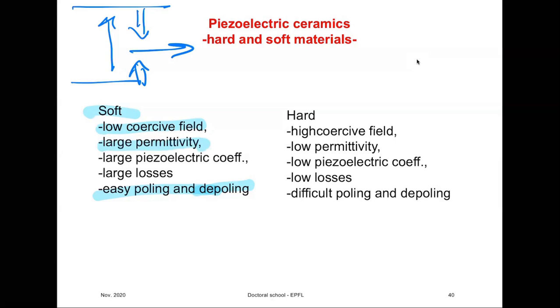They have large permittivity, which is good for many applications, and large piezoelectric coefficients, but they also have large losses. So at higher frequencies, they would heat up easily. Now those losses, electrical losses but also mechanical losses, are due to domain walls. You will see that domain walls in soft materials are very easy to move. They are responsible for all this, so it's not due to conductivity.